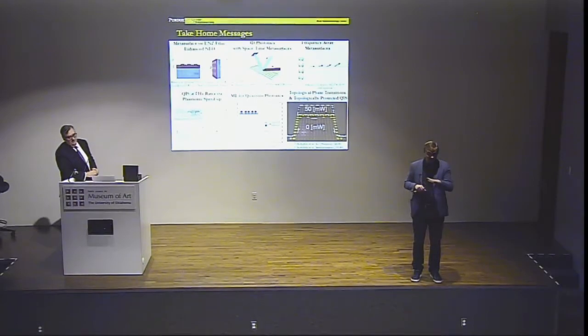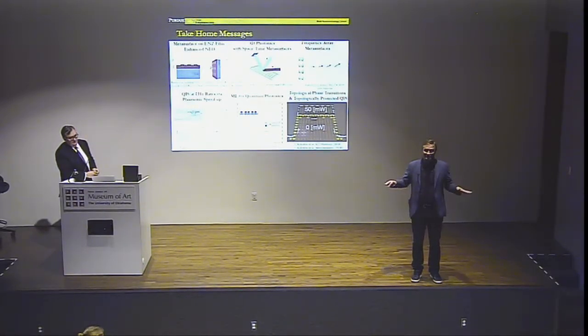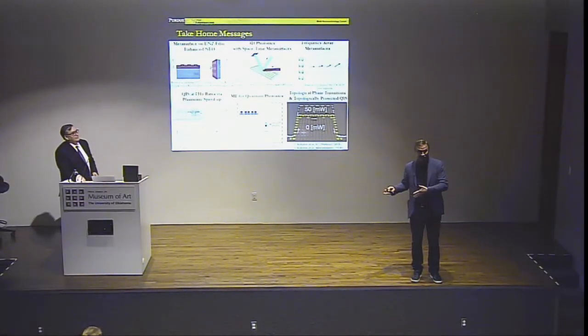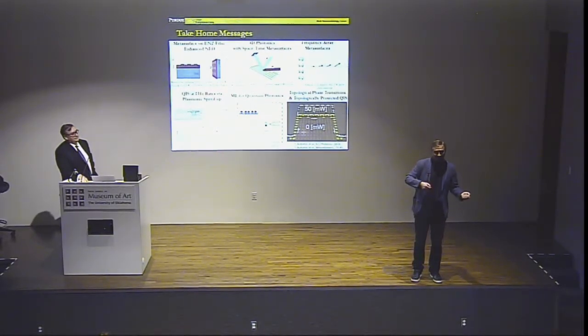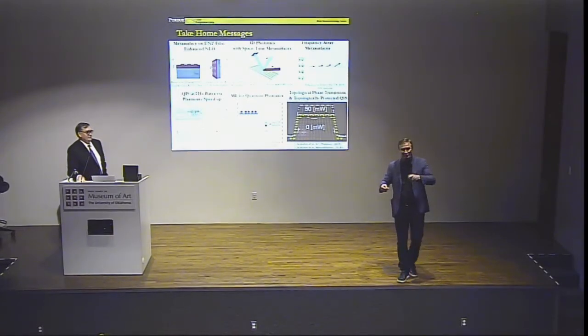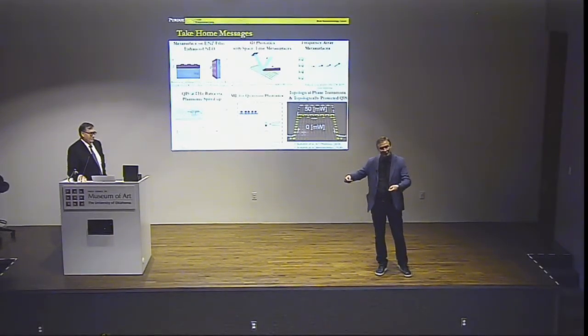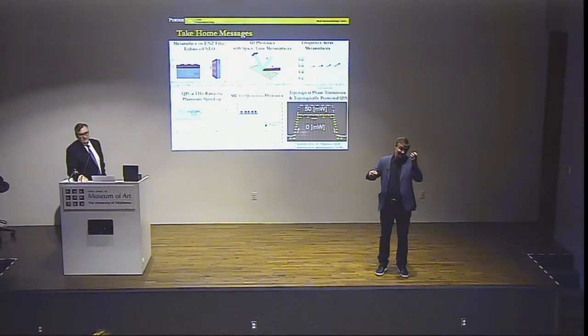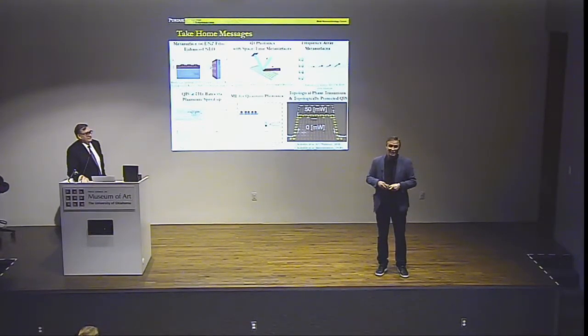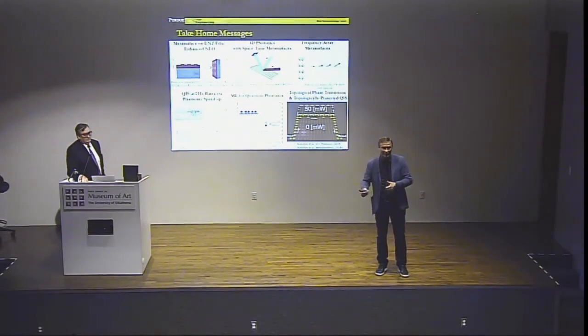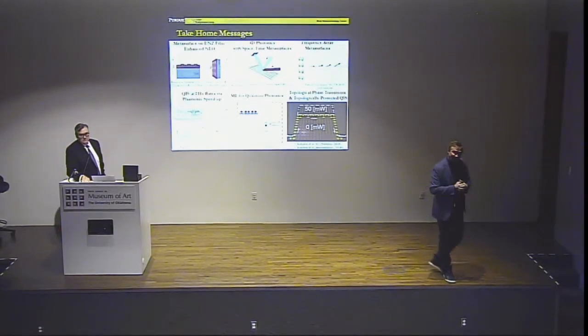With conventional Fresnel's law, which describes refraction and reflection, the interface does nothing in that regard. It doesn't break momentum, it doesn't break photon energy conservation. With my metasurfaces, I break both. If I modulate in the space domain, I introduce momentum and break photon momentum conservation. If I modulate in the time domain, then I break the photon energy conservation. So if I consider the metasurface and photonic system together, both momentum and energy are conserved. But for the photonic system only, they are not conserved anymore.